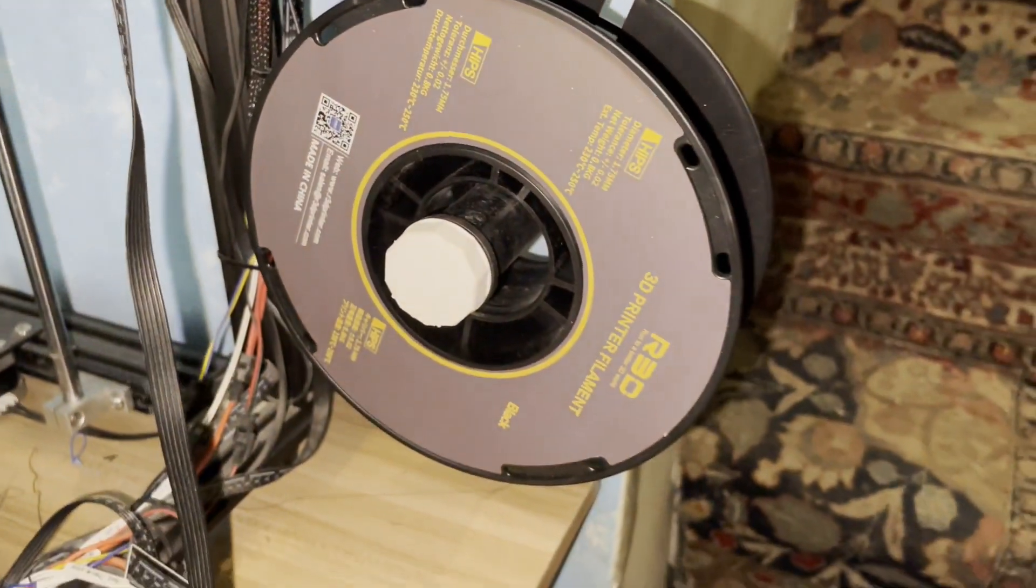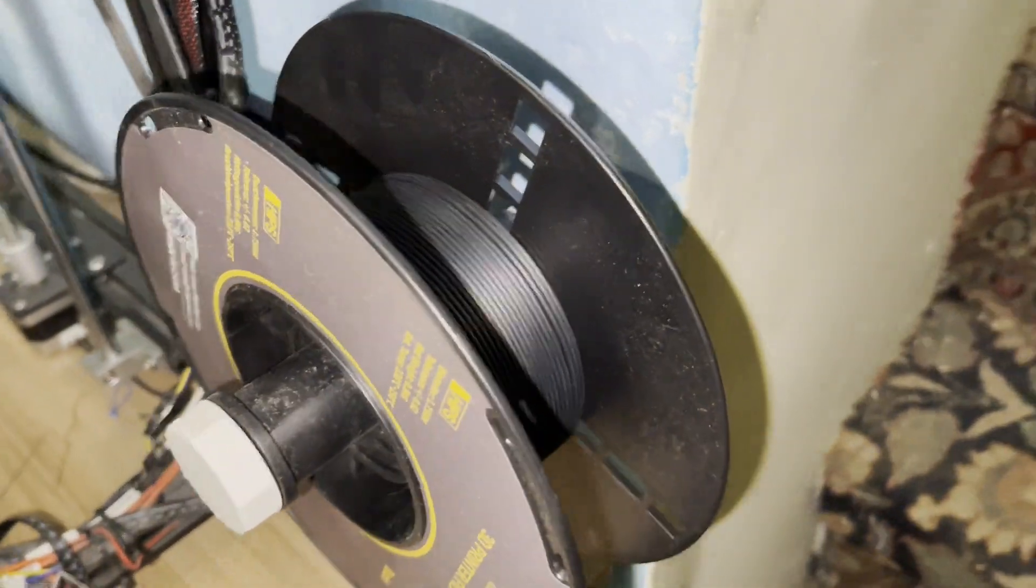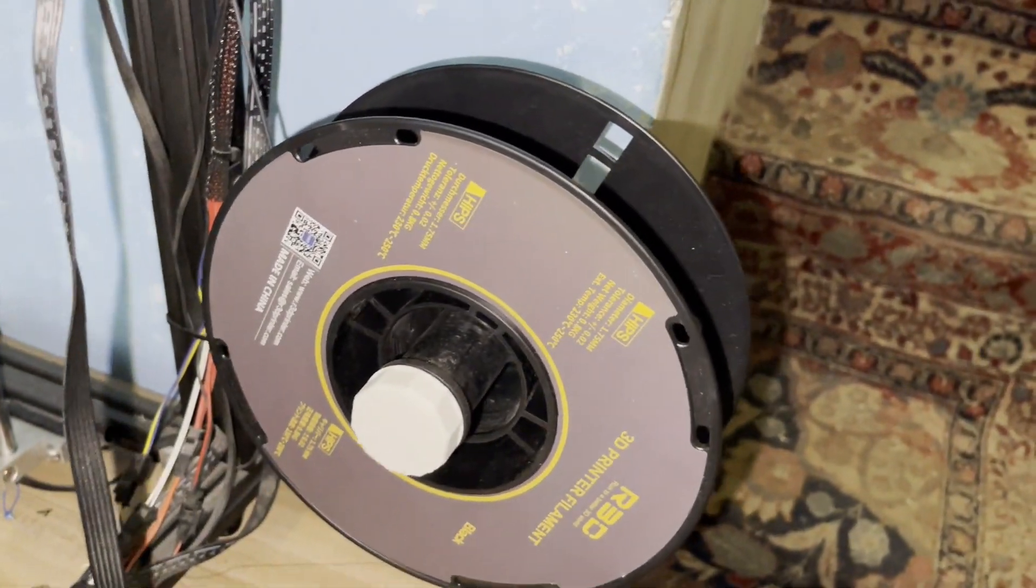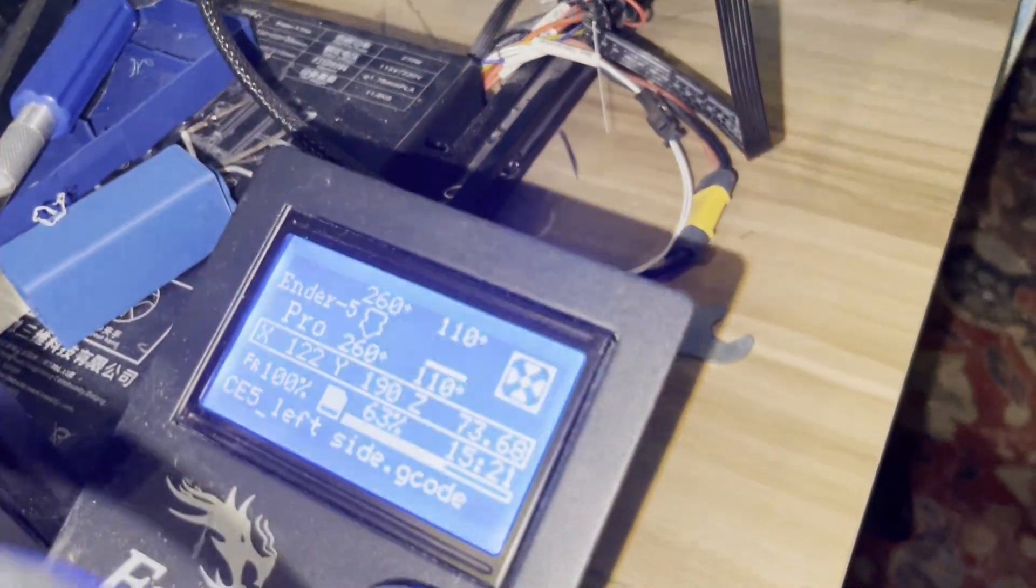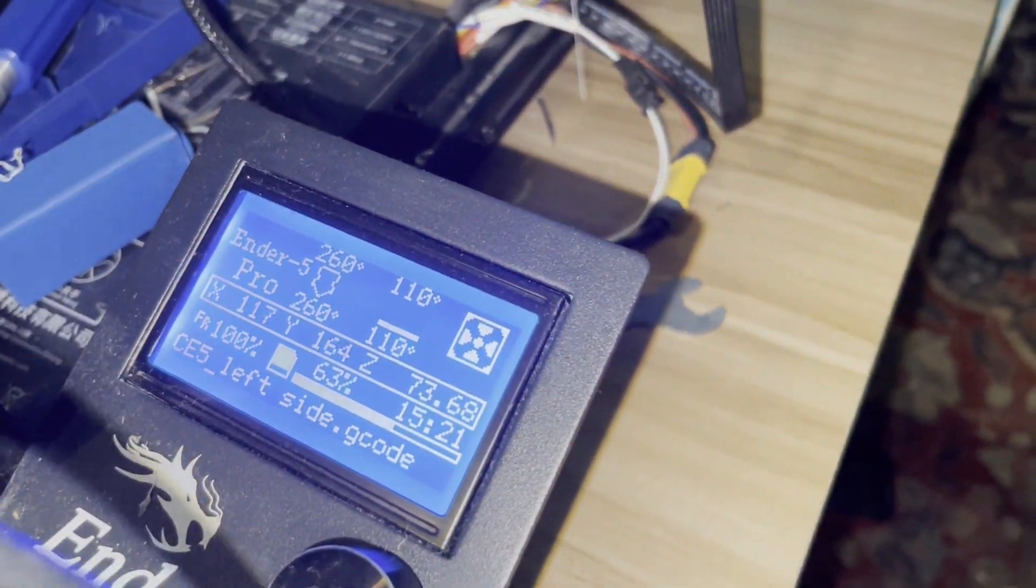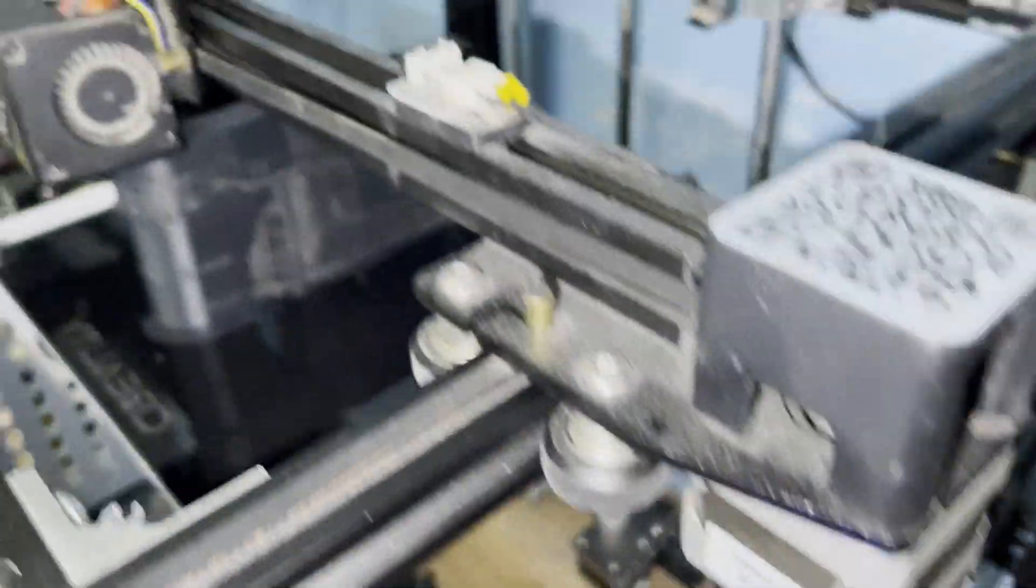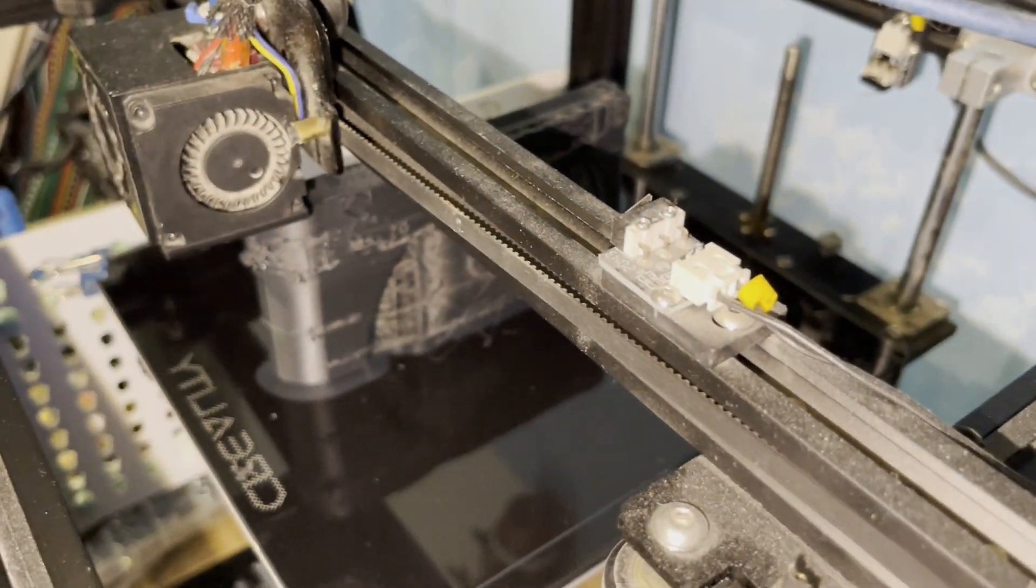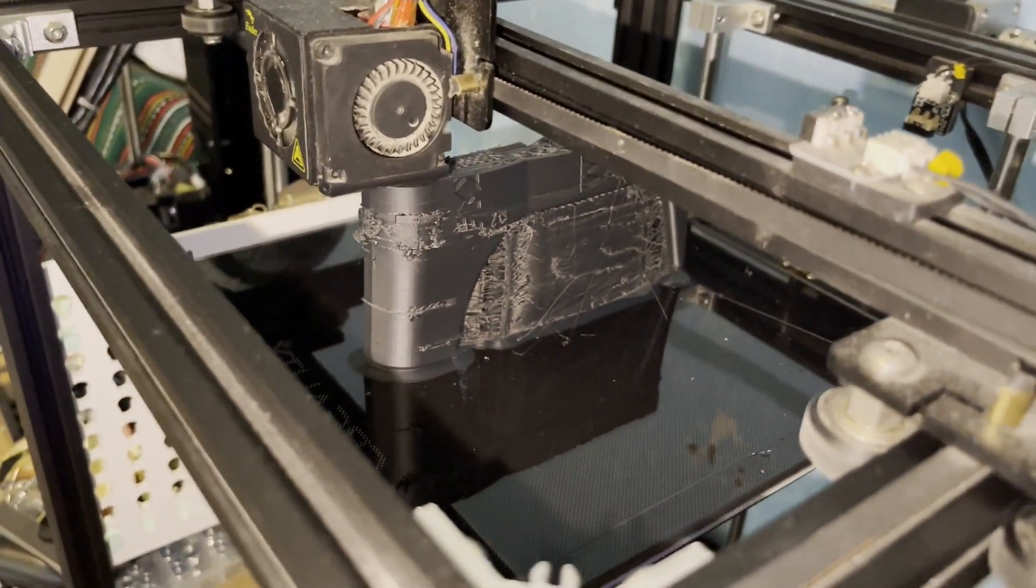I'm not an expert at printing with this filament. This is new to me. This is my first spool of one kilo. So I'm just experimenting, but this is what I figured out: you need a very high temperature, no fan, glass bed or something similar, and just give it a try.